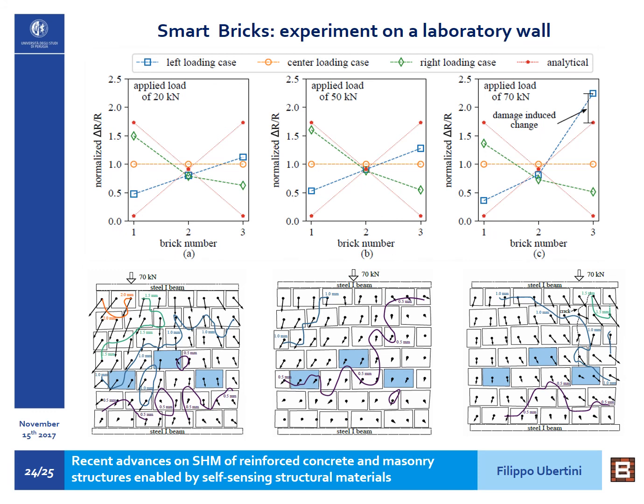But at least we see the same trend, where those results are expressed in the form of normalized changes in electrical resistance, where the normalization is with respect to the change in electrical resistance that we have for the centered loading condition. So in blue you have the case of a left loading, and in green you have the case of a right loading. What we should notice here is that when we have a load of 20 kilonewtons or 50 kilonewtons, the experimental results are very similar to each other. So as we expect, since those are normalized changes in electrical resistance, we don't have dependence on the applied load. We are in the elastic range.